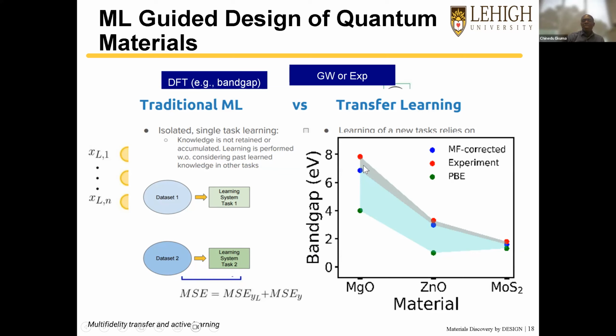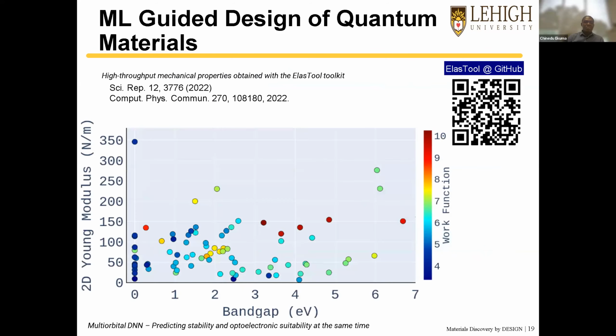As you can see, within our transfer learning, we are literally hitting the experimental data. This is within 3 to 5% of experiment, and that is good because that is where the experimental error bar is. So we can use this transfer learning to not only train on our data set, but make our low-level data set very accurate to enable us to make more informed decisions.